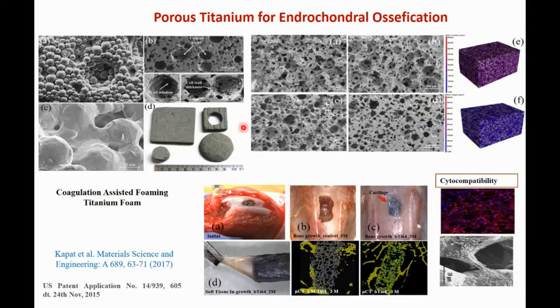But this porous titanium has randomly aligned porosity. By 3D printing, we can actually make the porous structure as per our need. So we can program them. We can make it as per our design. However, biological tissues actually favor the random structure. So we have made the random structure, and also we have made the 3D printed structure. We have done this with the tissues, and this is a powder metallurgy based process.